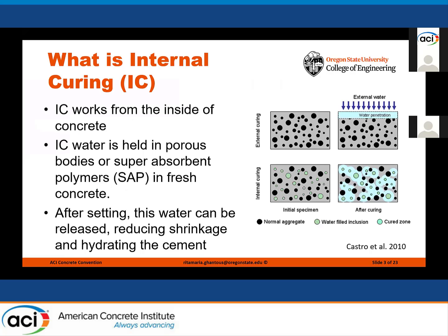Internal curing consists of storing water in reservoirs inside the concrete. These reservoirs can either be porous bodies or superabsorbent polymers. After the setting of cementitious materials, the stored water can be released, thus reducing the shrinkage and increasing the hydration of cement particles. So the use of internal curing in concrete has shown benefit in increasing the resistance to early age shrinkage cracking, which will enhance the durability of the material.